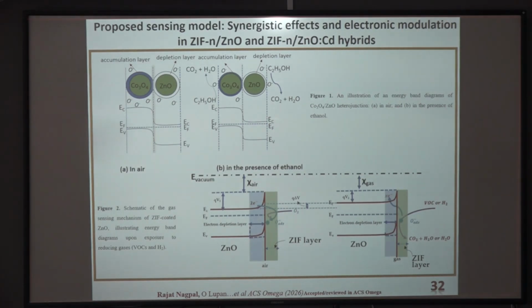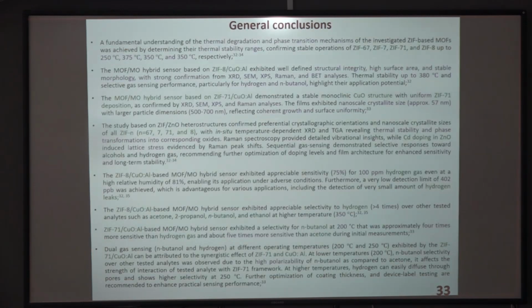So coming to the sensing mechanism part, as we have already observed, this ZIF-67 already transformed into cobalt oxide at 250 degrees Celsius. Using this model, we can observe change in accumulation layer width and depletion layer width in different environments, in air and in the presence of test gas, which leads to modulation in electrical resistance and hence sensing response. Using the ionization model, chemoresistive sensing can be understood easily, as we discussed.